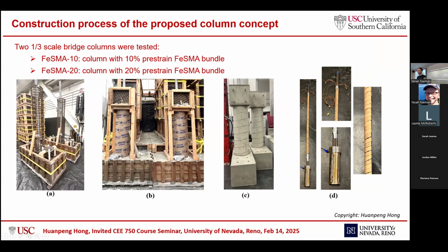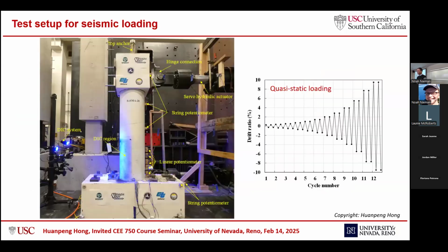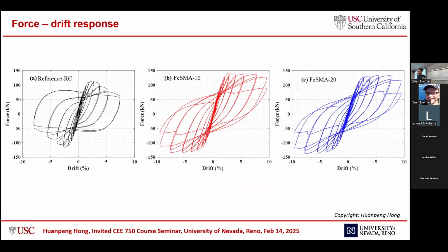We have a pre-stressed conduit in the middle, and then we put the iron SMA bar in the middle, and we wrap the heating tapes around the bars to heat the bars up, and we put a load cell to measure the post-tensioning force. So here's the setup we used for the seismic loading. We applied quasi-static loading to simulate earthquake loading condition. And this is the column, and also we use a lot of gauges to measure the response of this column.